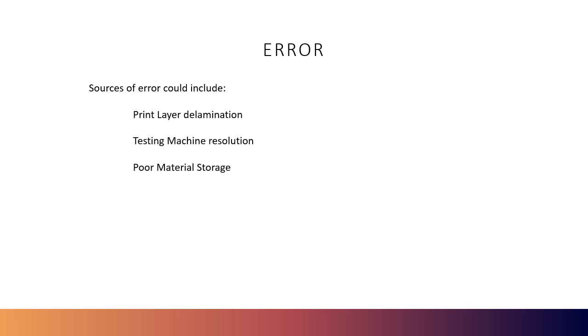As you saw in my results slides, there were some pretty significant errors compared to the published data on nylon especially, but also the 2 other filaments. I think the main source of that is this print layer delamination. I got some severe delaminations on those break surfaces, 50% plus of the area. I have no idea why.